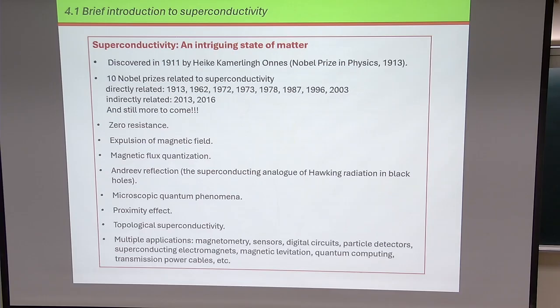So one of them, for example, is topological superconductivity. There is a candidate for topological superconductor, which are the P-wave superconductors. There is no P-wave superconductor in nature as far as we know. There are some candidates, but the Tc is so small that it's very difficult to prove that they are really P-wave superconductors. But you can engineer it by using the proximity effect. You can get some interaction from one material, superconductivity from the other, and engineer these P-wave-like superconductors.